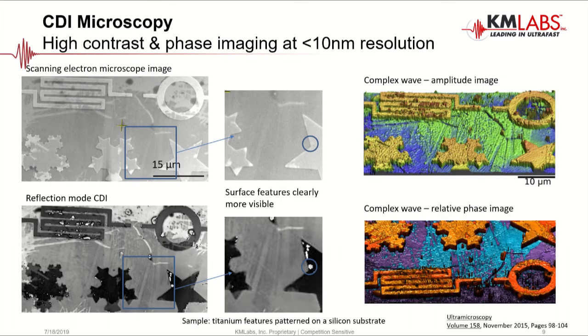This is an example, one result using this CDI imaging technique, and I'm drawing a comparison here to SEM just to get a little bit of a sense of the relative capabilities. The SEM images are shown on the top left. What we're looking at here are titanium patterns put down on a silicon substrate, and clearly there's also some other compositional variations going on. But we can see the SEM on the top left, reflection mode CDI, as I had just described on the last slide, shown on the bottom left. And you can see, of course, we can see the same features.